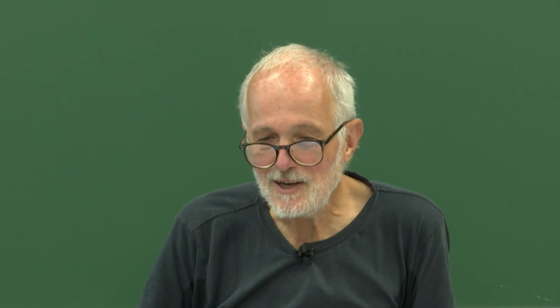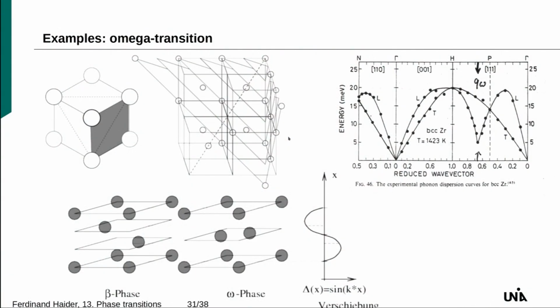And now, if you plot these 1-1-1 planes into the cubic lattice, you slightly displace them against each other. One plane slightly shifted up, the other one slightly shifted down. So if you shift this down and this up, then you obtain the hexagonal plane. So you have the stacking A, B. If you merge these two planes, A, that's the stacking of the hexagonal phase.